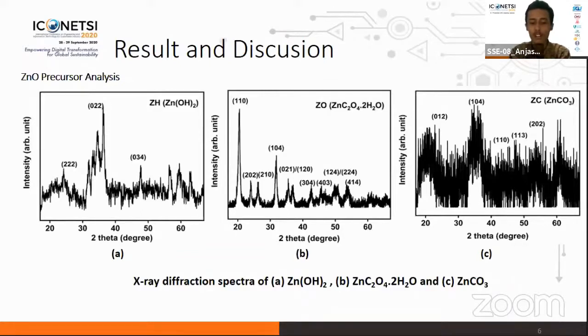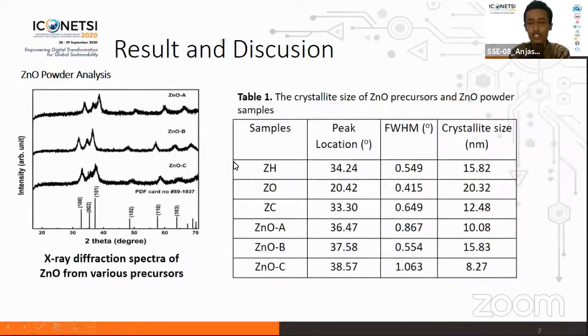All of the diffraction peaks are in agreement with the zinc carbonate diffraction pattern with trigonal structure, which corresponds to PDF part number 83-1765. The spectra of sintering of various precursors can be seen in this figure.